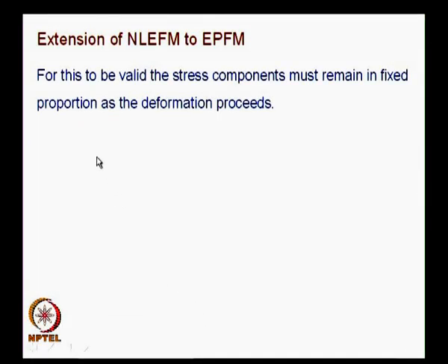And for unloading not to occur, or if you want to extend the concepts of NLEFM to EPFM, the stress components must remain in fixed proportion as the deformation proceeds. This is called proportional loading, we will see that in detail. So, in all fracture mechanics literature, you will come across the terminology proportional loading when you are discussing concepts related to EPFM. And what is proportional loading?